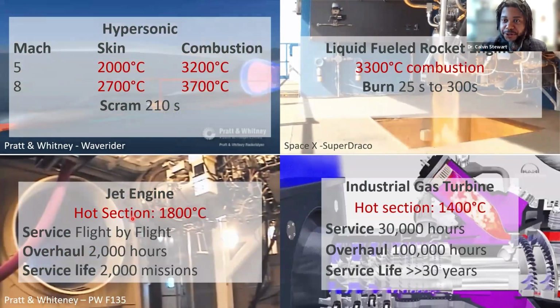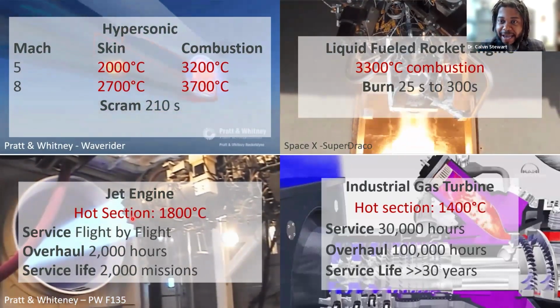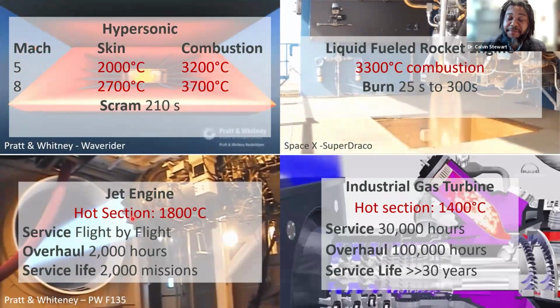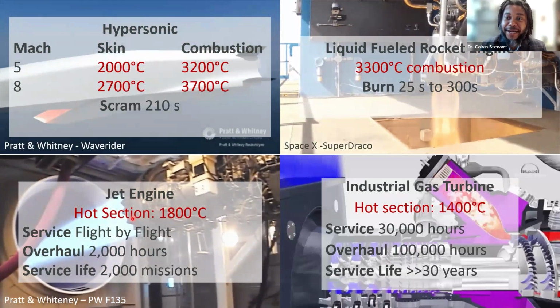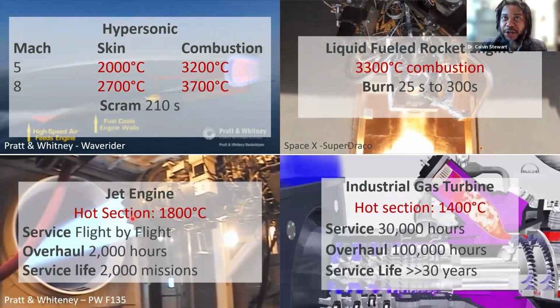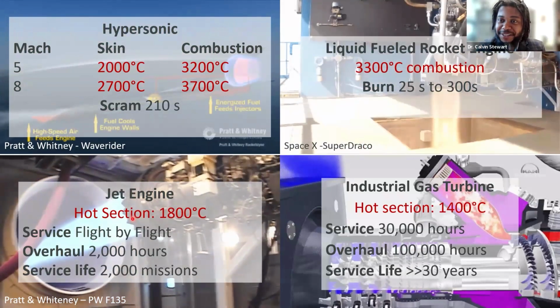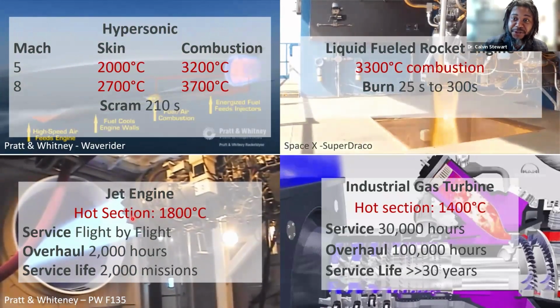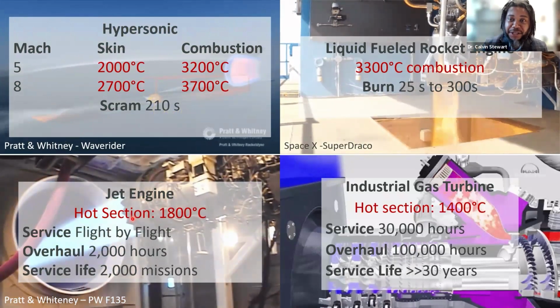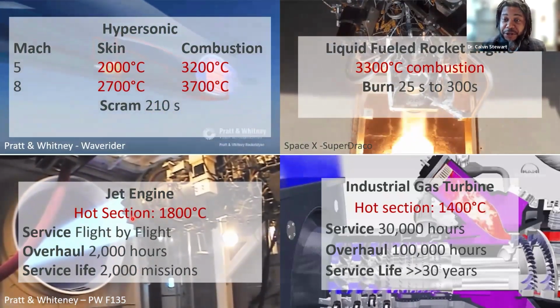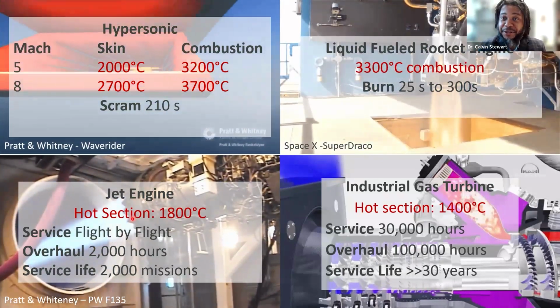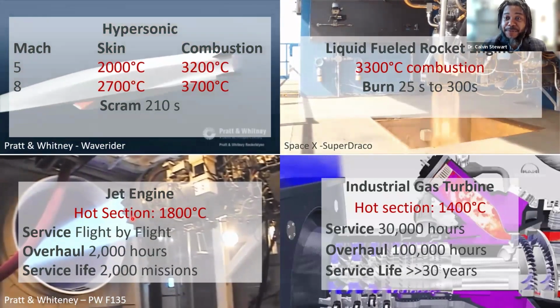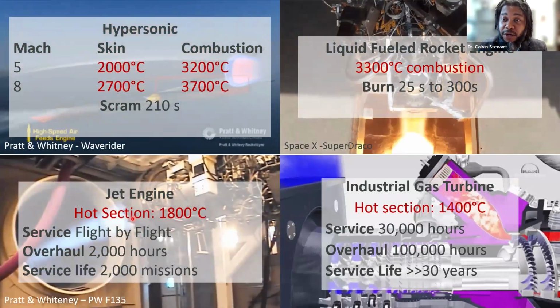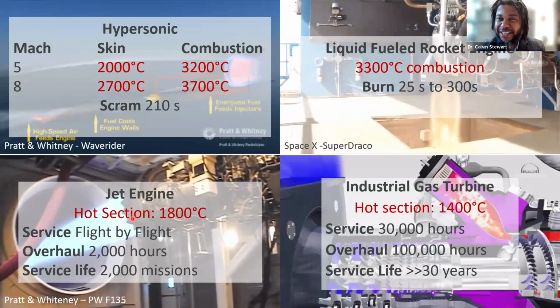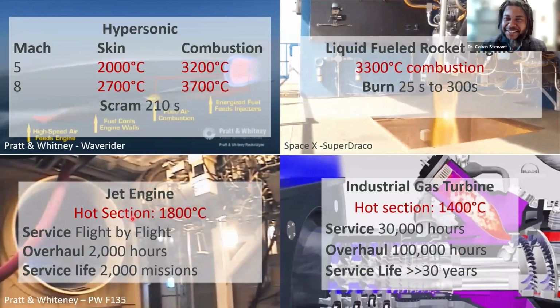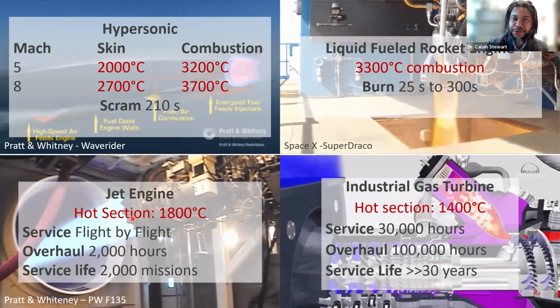In all of these 4 use cases, these are materials that are being asked to survive above the base metal melting temperature. Nickel superalloys melt around 1,200 to 1,300 degrees Celsius. So in every one of these cases, the base metals or the base materials we use would actually melt in reality. And so what do we do? We take our monolithic materials and we coat them in thermal barrier coatings. We core them out and install internal cooling passages. We may even bypass air across the skin of these components to create a cool layer that keeps them from melting. But in all cases, we are beyond the limits of the material's capability.